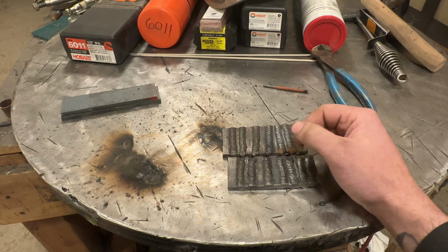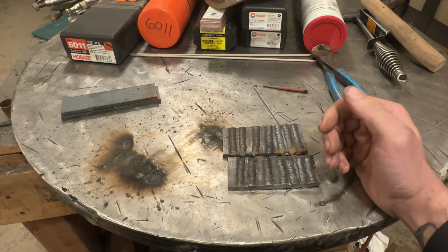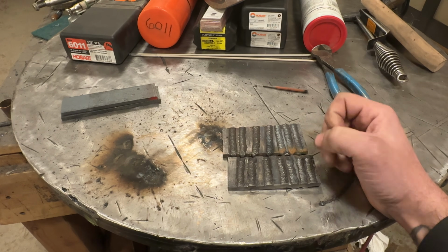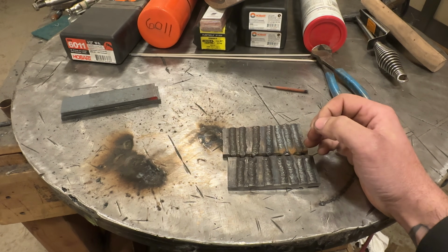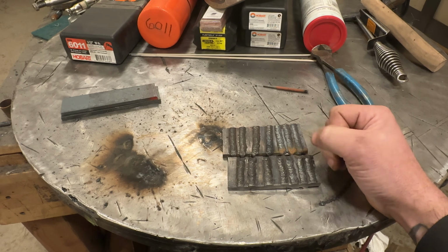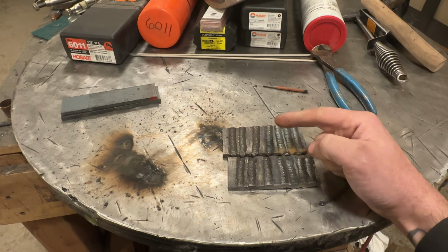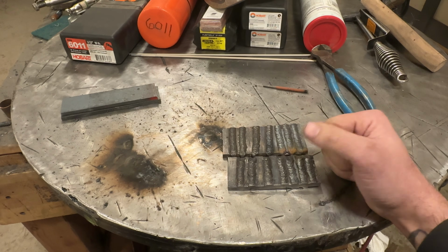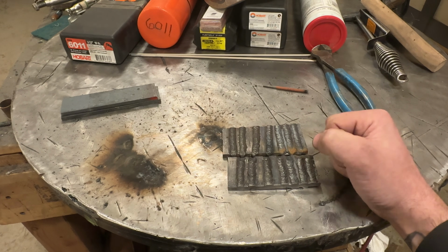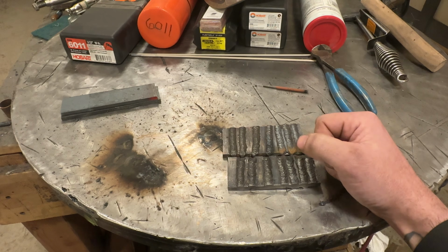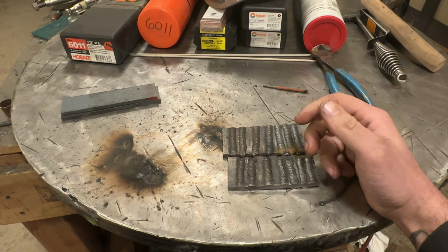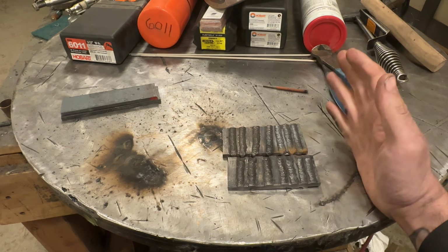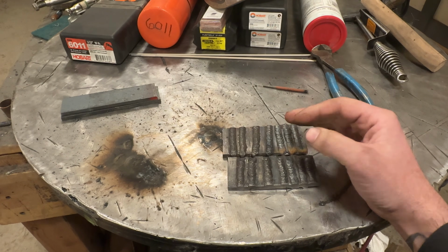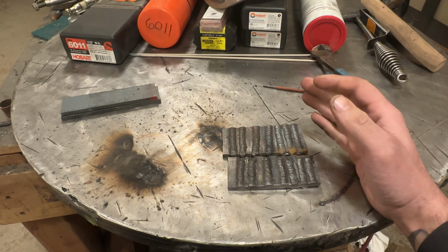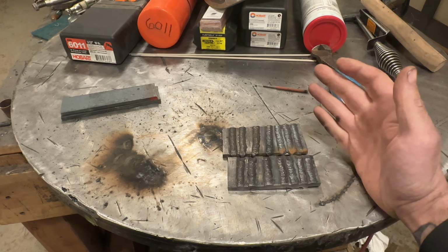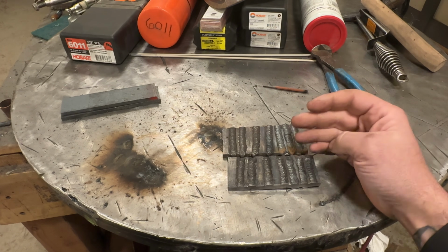Now, with 6011, like you saw, if you don't run it at a high enough amperage, which I find is a little bit over 6010, you will have severe penetration issues. When I was welding that, where it was beaten up like caulk, what I should have done is break the arc, turn the machine up 10, restart, and that would have solved that. But hey, it was pretty cold, and the cut and etch was probably eye-opening for me, probably for you too.